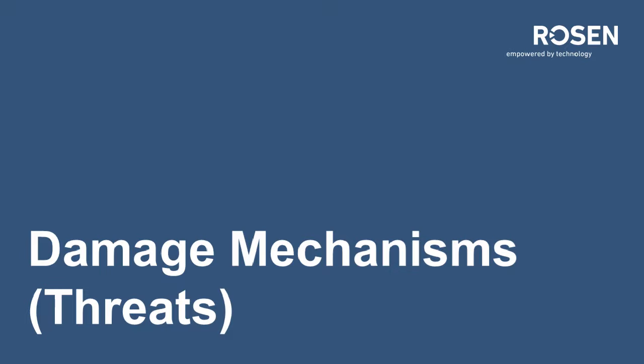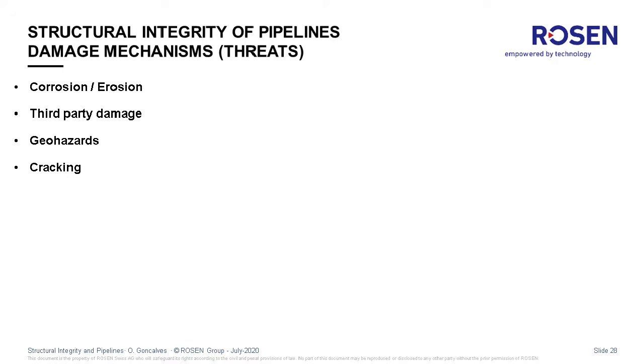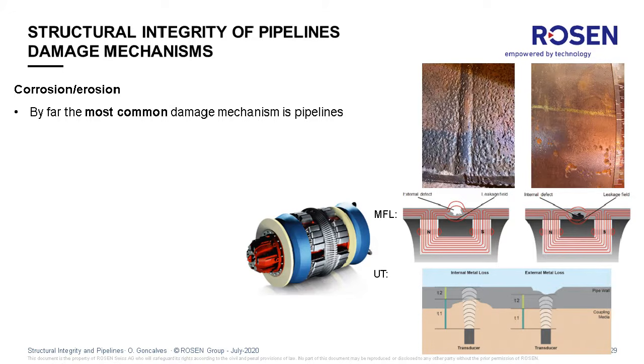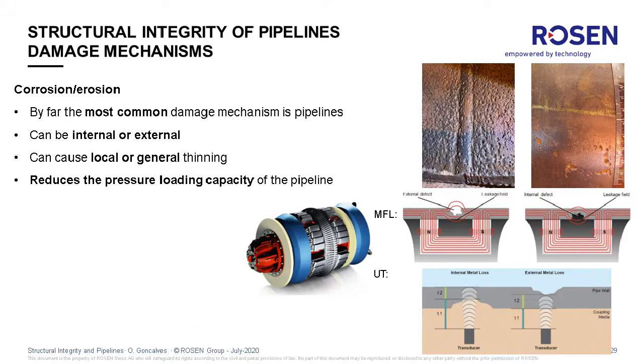So now I'm going to talk a bit about damage mechanisms and still a bit about inspection. The main damage mechanisms are corrosion, erosion, third-party damage, geohazards, and cracking. Corrosion and erosion is by far the most common damage mechanism in pipelines and can occur both internally and externally. The causes, of course, are different. On the internal side, it is associated with the product being transported, and on the external side, it is associated with the interaction of the metal surface with the soil, if there is a flaw in the coating, and if the cathodic protection is not effective at that specific location. It can cause local or general thinning. The consequence of the corrosion is a reduction in the capacity of the pipeline for loading in terms of pressure, and it can lead in the end to a leak or a failure, depending on the dimensions and the mechanical properties of the pipe.